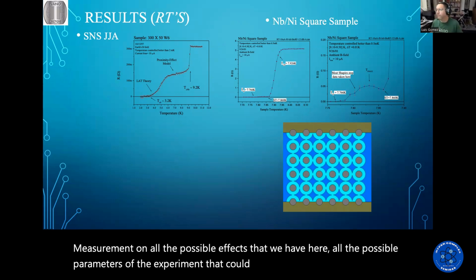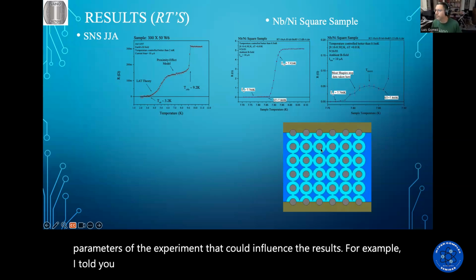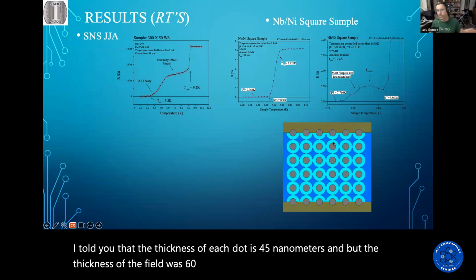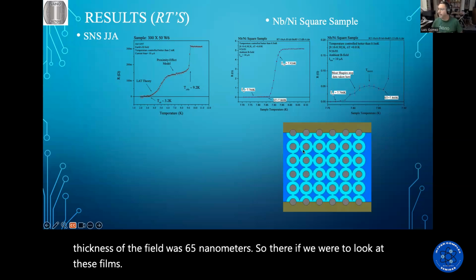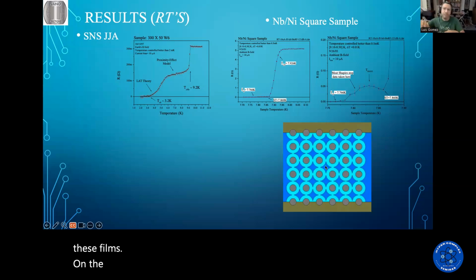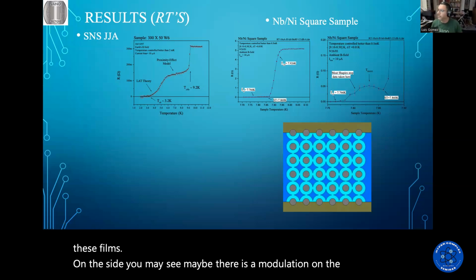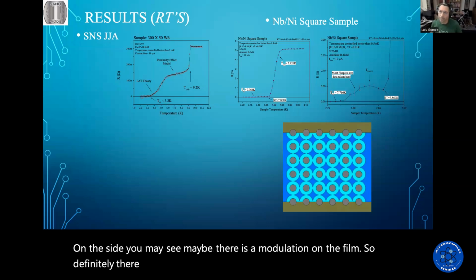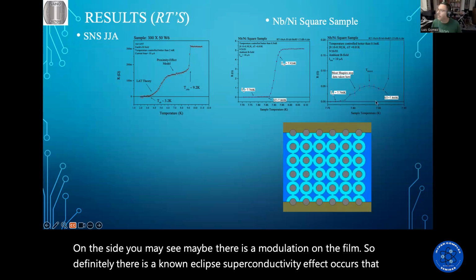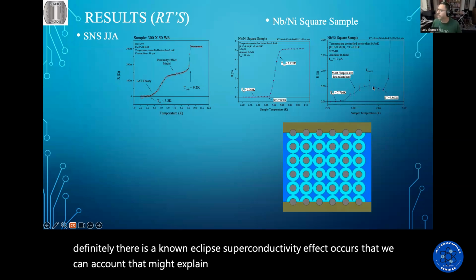For example, I told you that the thickness of each dot is 45 nanometers, but the thickness of the film was 65 nanometers. So if we were to look at these films on the side, you might see a modulation on the film. So there is definitely a non-equilibrium superconductivity effect that occurs that might explain what is happening.